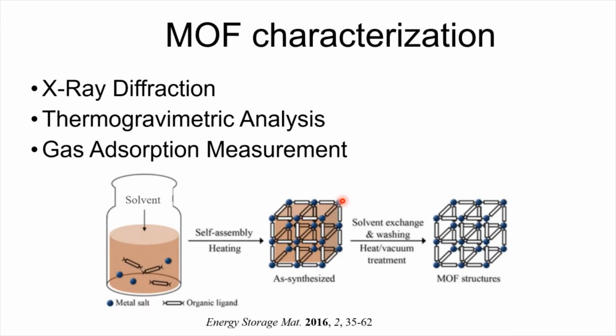Now, in most of these materials, since they are porous, they will most definitely have solvent residue inside. And that's when you use thermogravimetric analysis to know exactly at which temperature you get rid of the internal solvent. And it also tells you the thermal stability of your structure. And finally, once you have those empty, nice pores, you do the gas adsorption measurement. That will tell you how easy, and what sizes and shapes, those pores are.